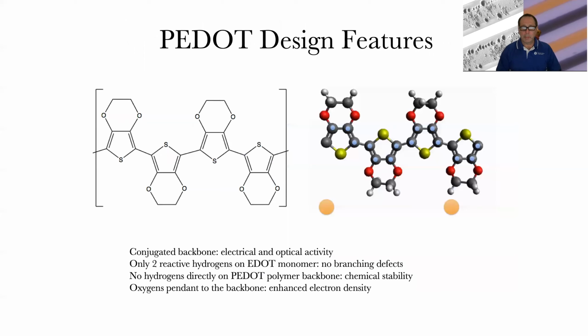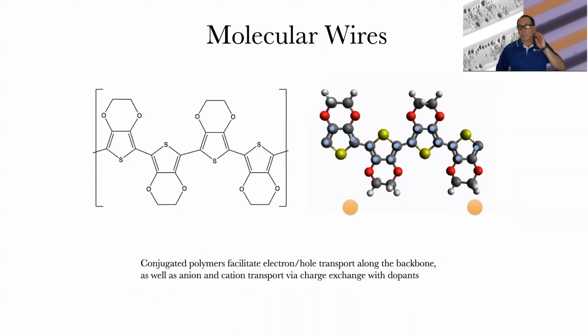Now, in terms of a materials design problem, the stability of this molecule comes from the fact that there's no hydrogens pendant on the conjugated backbone. And again, you get this transport where you have electrons and holes moving along the molecular backbone, and then some counterions that are putting a little bit of charge on the polymer backbone. So you get both electron transport and ion transport.